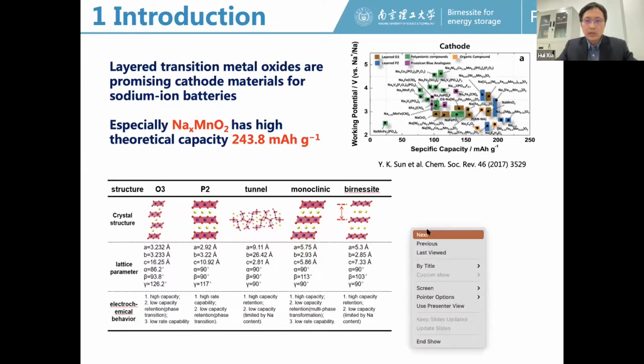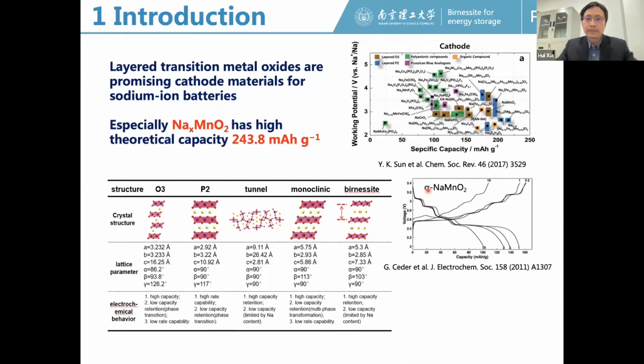And also when we look at the charge-discharge profiles for this monoclinic sodium manganese oxide, we can see many voltage plateaus during charge and discharge, indicating many phase transitions during the cycling. And we can see a fast capacity fading during the cycling, which indicates this layered structure is not stable.